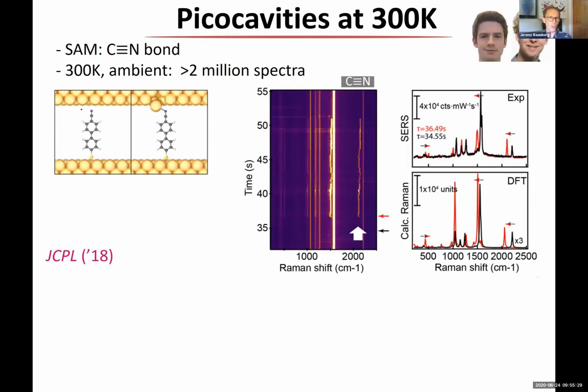So we can try this with a molecule which has got a CN group at the end here. So this CN group is nice because it has a particular vibration around the 2200 wave number region of the spectrum. So we can see that on its own. And what happens is as soon as this gold atom gets pulled out, because the optical field is very strong in the vicinity, we see only this particular bond here. So this line that I'm seeing here is a single CN bond. So now you can see single bonds at room temperature, and clearly it's shifting around all over the place. So that's what we've been able to understand more recently.